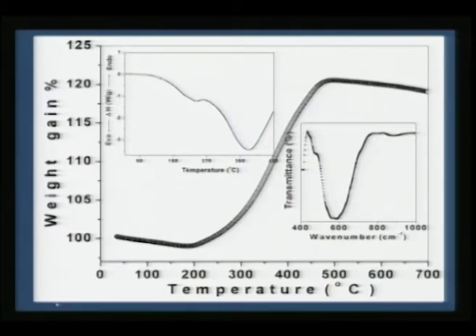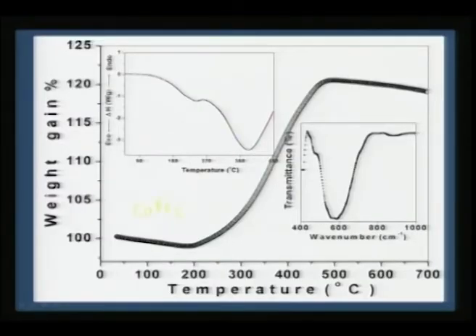Therefore, we can clearly prove that it is so, but from a chemist's point of view it is much easier for us to ascertain whether it is really the alloy or the oxide itself. How do we do that? Take the alloy powder that you prepare and try to do TG. Usually we are all familiar that with TG, we always think about weight loss when you heat any sample, but if you are actually going to take CoFe2 and heat it in air, then you would not expect a weight loss, but you should expect a weight gain because it is going from CoFe2 to CoFe2O4.